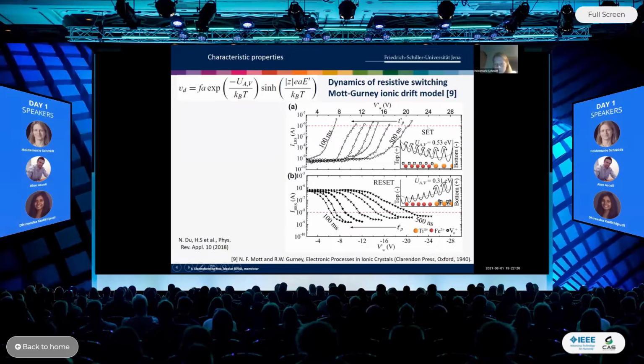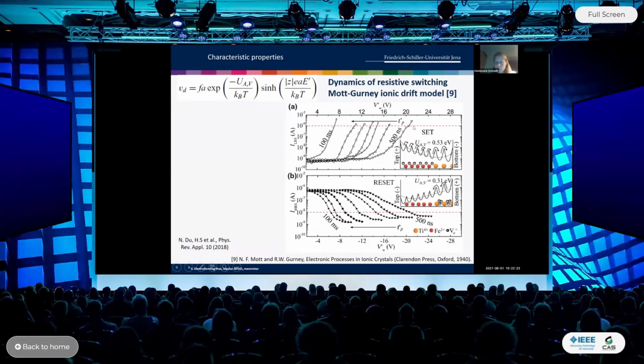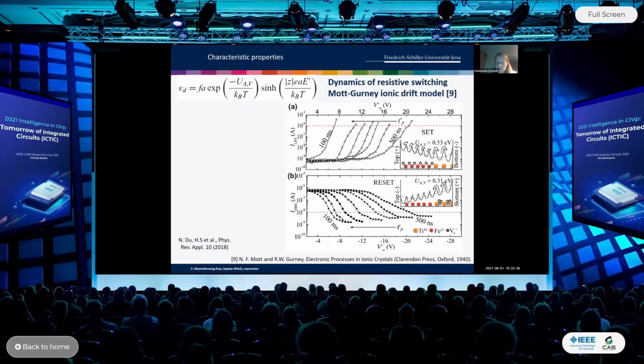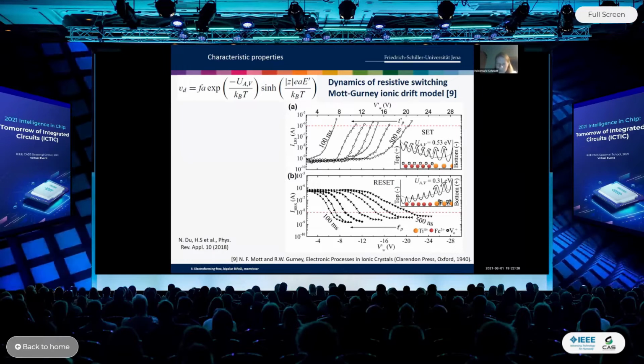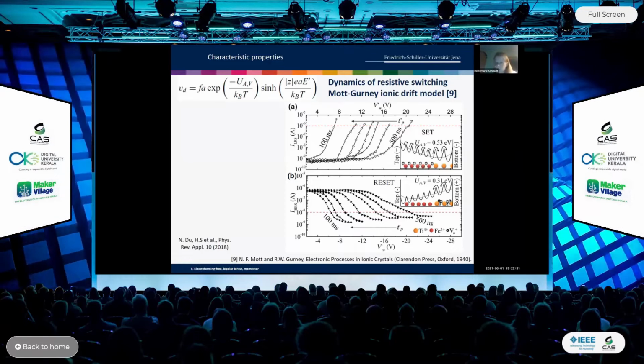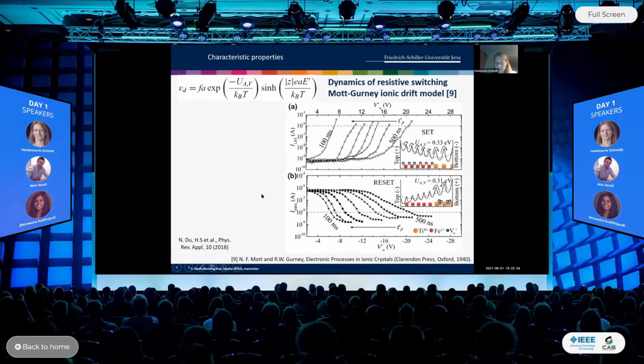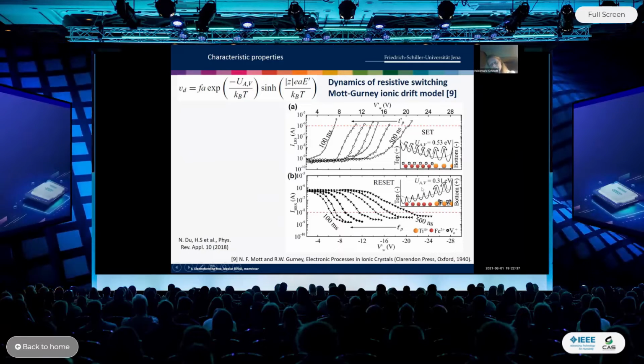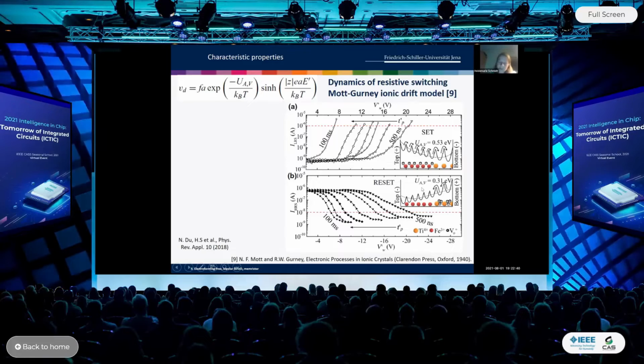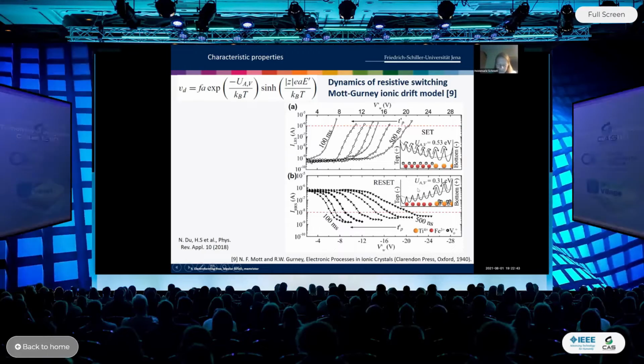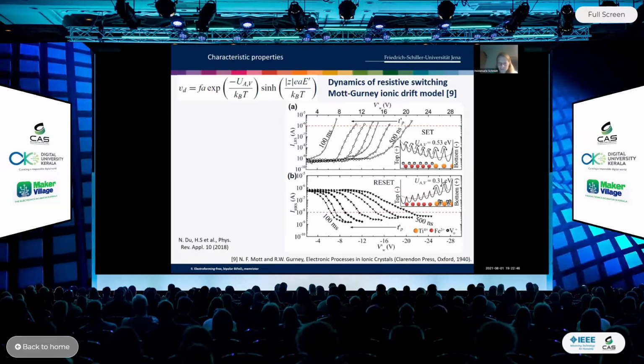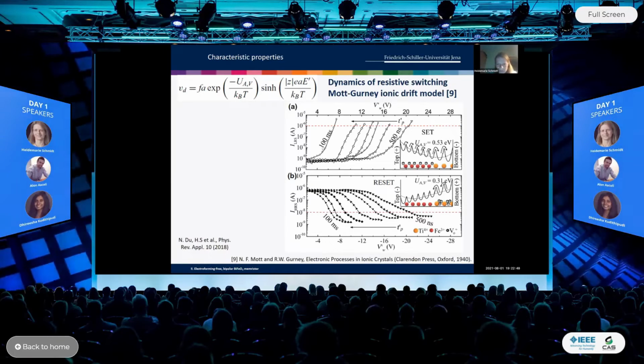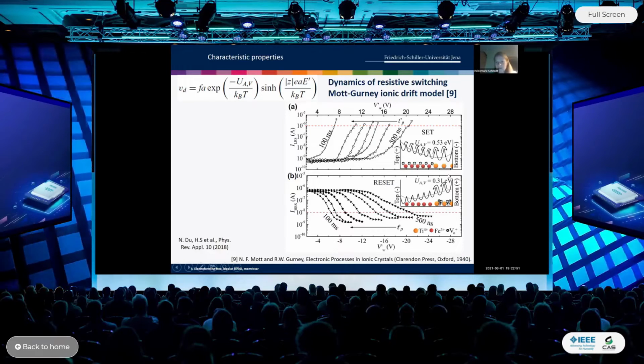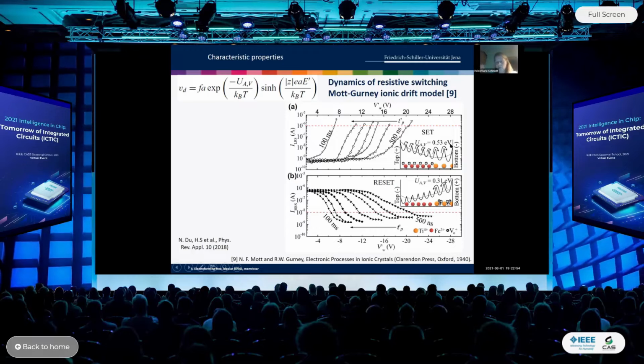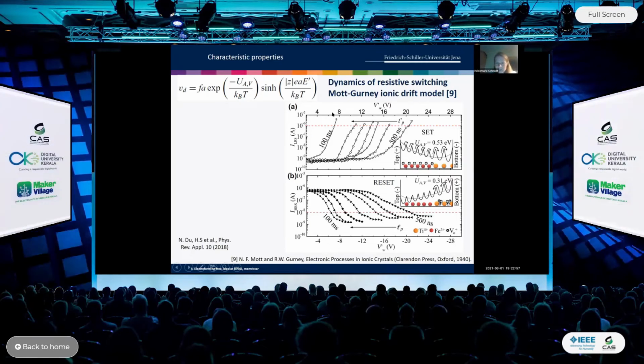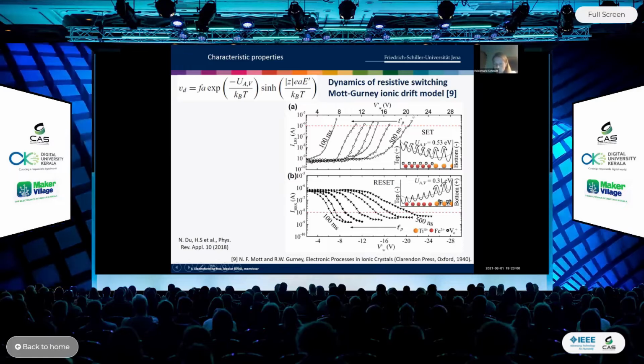So they are of interest now in the experiment I'm showing here, because we wanted to determine: is it indeed possible to increase the velocity of writing, the writing speed in the system, tremendously just by changing the electric field we apply? We had two parameters we could vary. If we apply a rectangular writing bias pulse, then we can vary the length of this pulse, for example, between 100 milliseconds and 500 nanoseconds, and the amplitude of this writing bias. Here we vary it between 6 volt and 22 volt, as you can see.